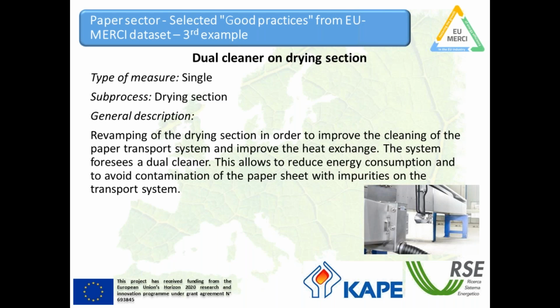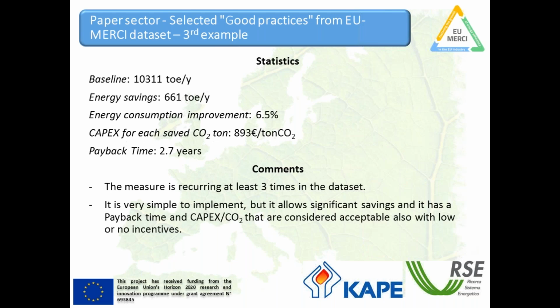This system of double cleaning is very easy to install on the sides of the machine, as you can see. And here we had more than one intervention. We had at least 3 times with exactly the same intervention. So here we have again the average. We can see that the baseline is very high because drying is a very energy intensive part of the paper making machine. Energy savings are high, but if we consider the relative energy consumption, the improvement is just 6.5%. It's not bad, but it's not the most perfect one.